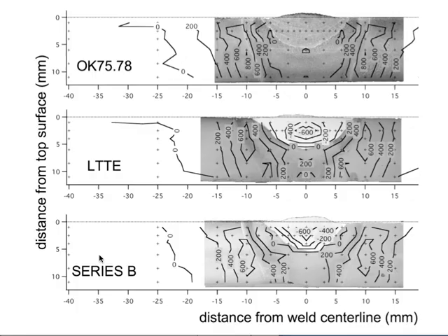So these tests are done at Chalk River in Canada, and we have here the high temperature transforming material at the top, and you can see the longitudinal residual stress contours. And if you look at the low temperature transforming, you might see that there's a minus sign here. Okay, so that's a compressive stress. So it works when you actually make the weld itself, right?